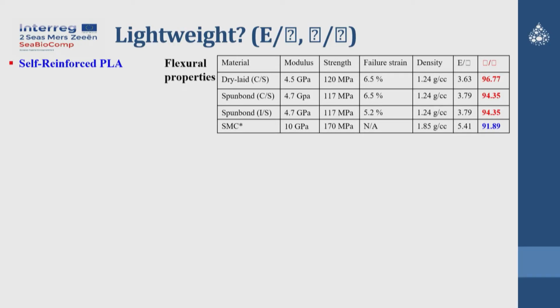I'm sorry, some letters are cracked. Anyhow, the question is, compared with conventional composites, can all these bio-based composites contribute to lightweight design? It is true that, for example, self-reinforced PLA has lower mechanical properties than the conventional SMC. You can see that the modulus is lower and strength is also lower than SMC. But you cannot ignore that this self-reinforced PLA has very low density.